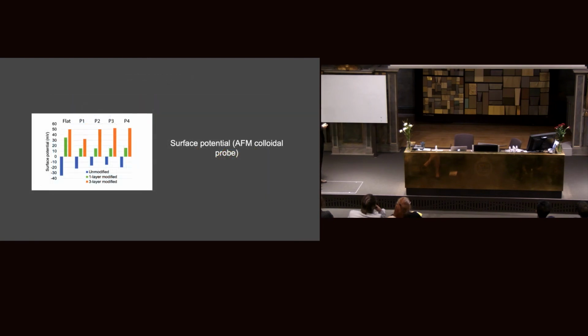We also determined the surface potential using AFM colloidal probe, and we found that for the unmodified surface and one-layer modified surface, there's a big difference between the surface potential of flat surface and pattern surface. But after three-layer deposition, it becomes closer, which is good because we want to compare different structures at similar charge densities.